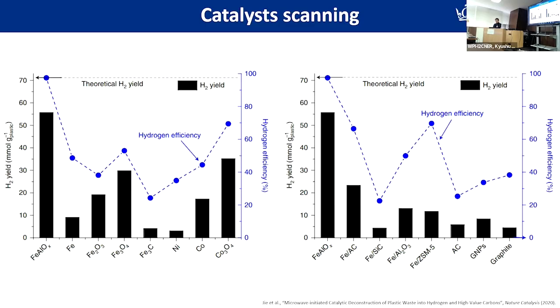And as you can see, we also studied the iron particle alone, iron oxide, hematite, magnetite, and iron carbide, because lots of research proposes that iron carbide is the seed for carbon nanotube growth. And in our research on the iron aluminum oxide, we do find the formation of iron carbide. So we wondered whether the iron carbide serves as the active compound for this reaction. But when we prepared the iron carbide and used it as a catalyst for this particular reaction, we found, no, perhaps that is not the right candidate for us.